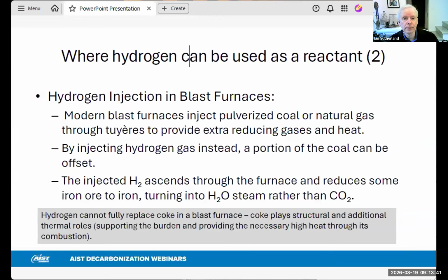Hydrogen can also be injected into blast furnaces. However, there is a practical limit to how much hydrogen can be used because excessive hydrogen use cools the furnace due to the endothermic reaction that takes place and the high heat capacity of the water vapor that is formed. And this could destabilize the furnace's operation. So a hydrogen injection might reduce by 20 to 30% the carbon dioxide emissions for a blast furnace, but it will not achieve zero carbon iron on its own.